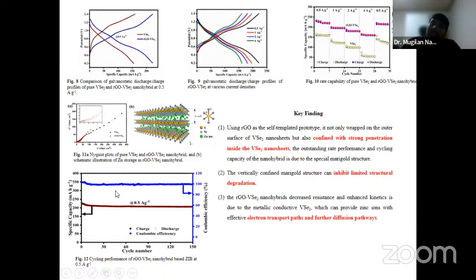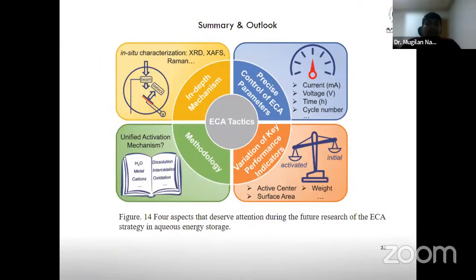The cycling performance gives 97% capacitance retention, which is highly favorable for confined strong penetration of ions. In the key findings, we found that the confined strong penetration of VSe2 nanosheets gives outstanding rate performance. The vertically confined marigold structure still inhibits structural degradation, and it also helps the electron transport pathway for further diffusion pathways. These are the major things to be concerned with when we are focusing on zinc ion batteries.